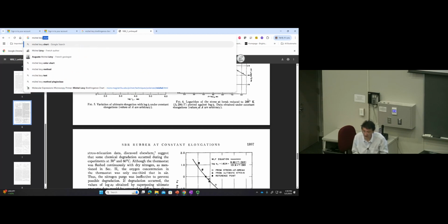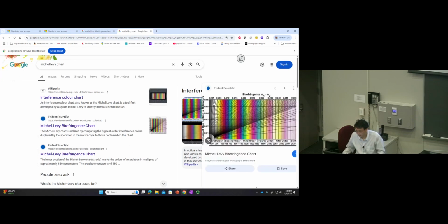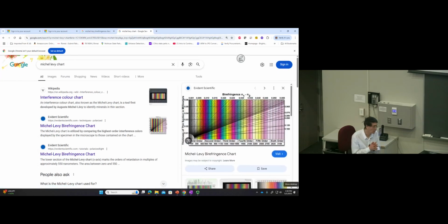we know polymers are chain-like, in the sense that if you look at a single chain, they are not optically isotropic. There is an extraordinary light and ordinary light. Depending on which way the light is polarized, it will propagate with different speed if you have a chain like this. But of course, when your chain is in the coil form, it's isotropic because it's all averaged out.